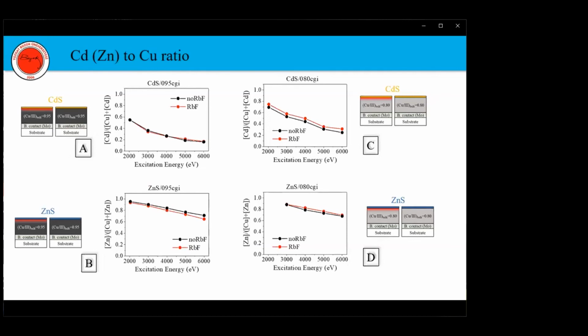Another important aspect is the diffusion of buffer layer elements into the absorber. One of the well-known phenomena in CIGS solar cells with cadmium sulfide buffer layer is that the high efficiencies are attributed to cadmium diffusion into copper vacancies of the surface near region during the chemical bath. Now here, if we compare figures A and C, one can see that the relative cadmium concentration with respect to copper is higher in case of the copper poor sample in figure C already before PDT. This is a direct indication for a copper vacancy assisted cadmium diffusion into the topmost region of the CIGS absorber.